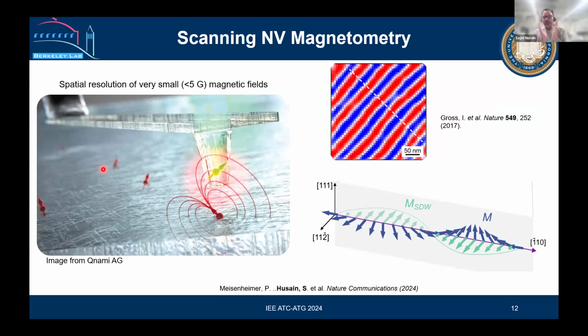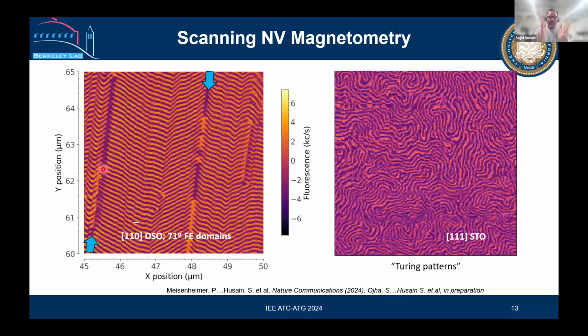And these magnetic domains are very small, because the magnetic moment of bismuth ferrite is 0.045 Bohr magnetons, which is very small. We need a very sensitive technique. This is NV magnetometry. I don't want to go into the detail, but yes, we can do a clean imaging of such structures. So these are two images on the left and right. As I said, we can control these magnetic domains in different ways, like strain. On DSO, the dysprosium scandate substrate, we can have nice stripes. And when we grow on strontium titanate substrate in a different orientation, we see a Turing pattern. Turing pattern is a theoretical concept, a kind of pattern formation, natural formation in materials. So yes, we can control these architectures using materials engineering.